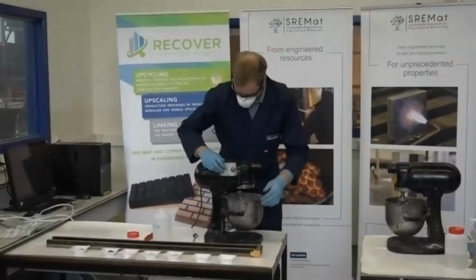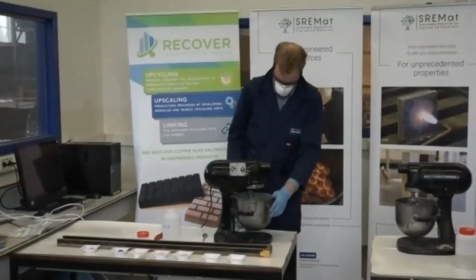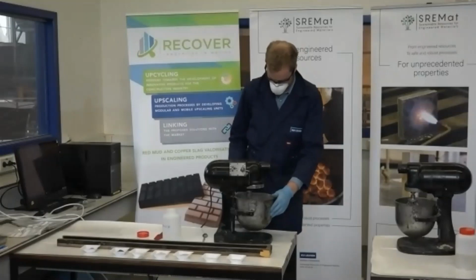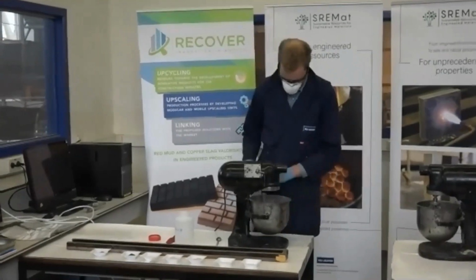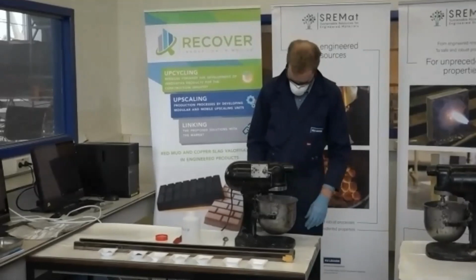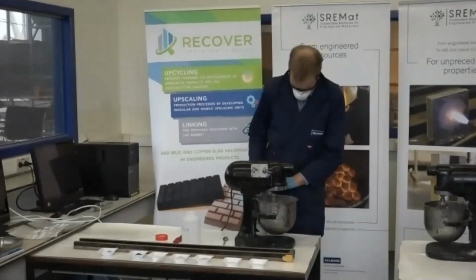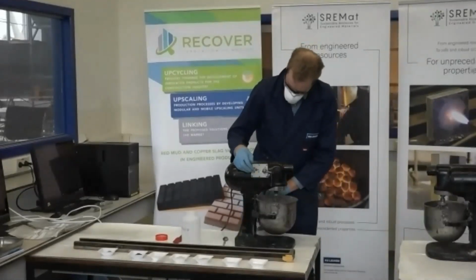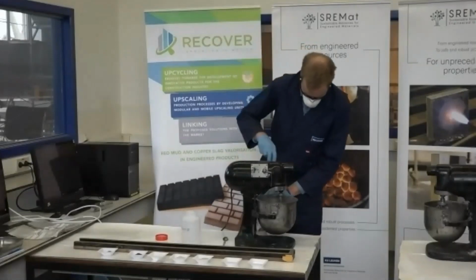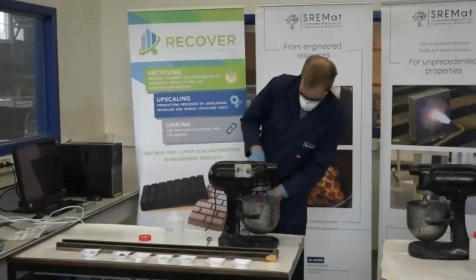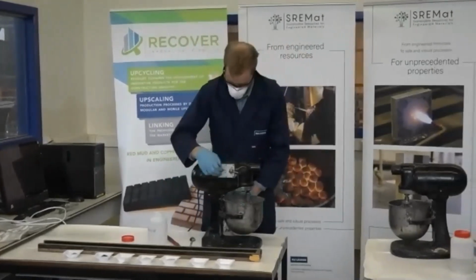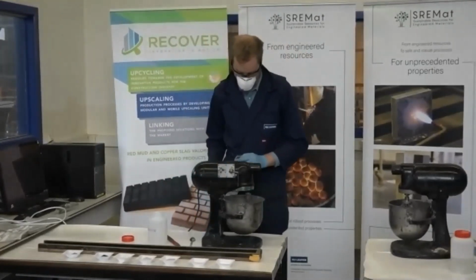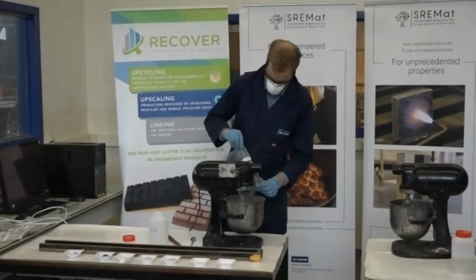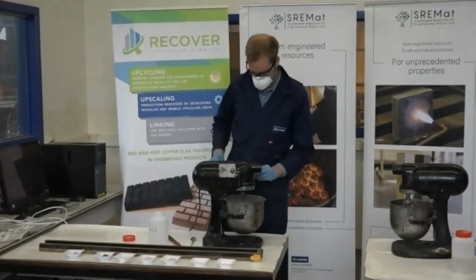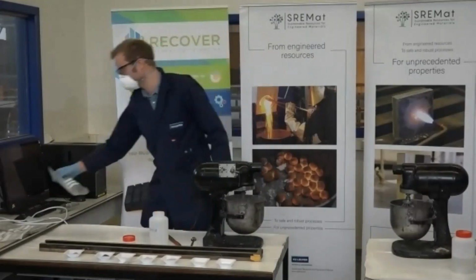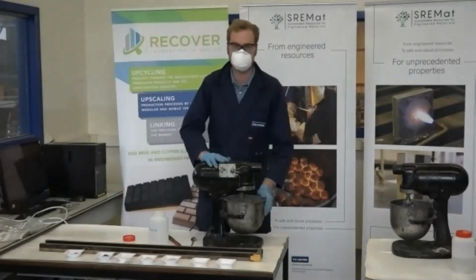And after a certain time of mixing, normally we always go to a higher mixing speed to really have a homogeneous mortar or paste in this case. You've also seen Michiel scraped a bit the sides of the bowl, the mixing bowl, to really have all the materials that he weighed in, also in that mix.